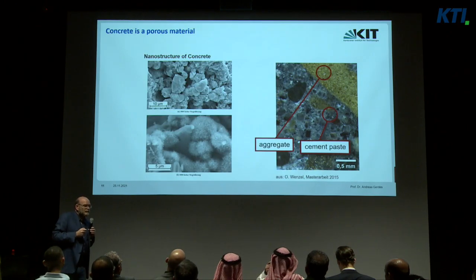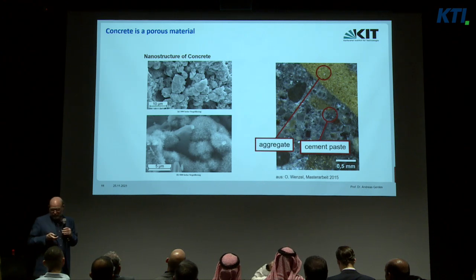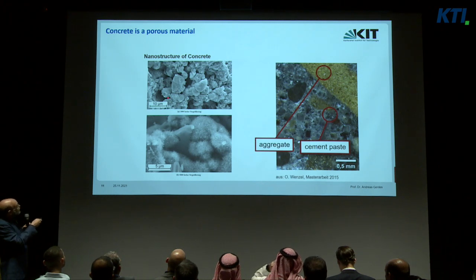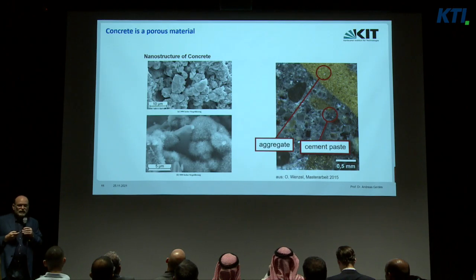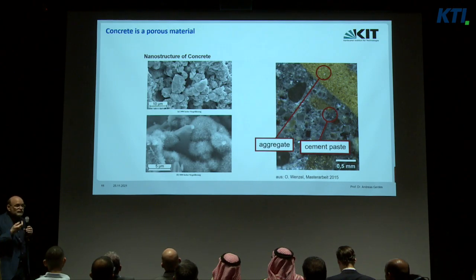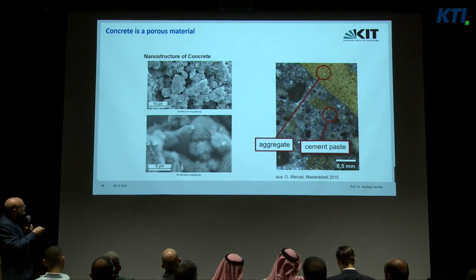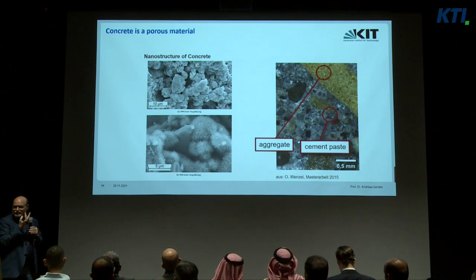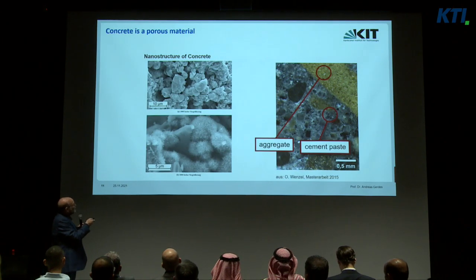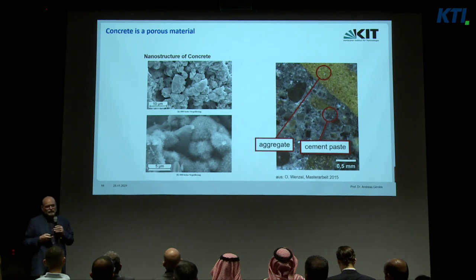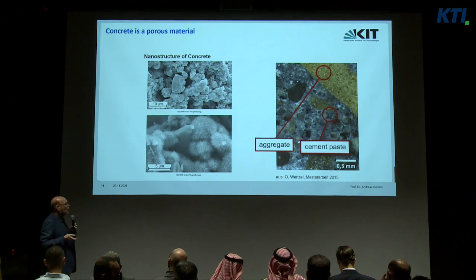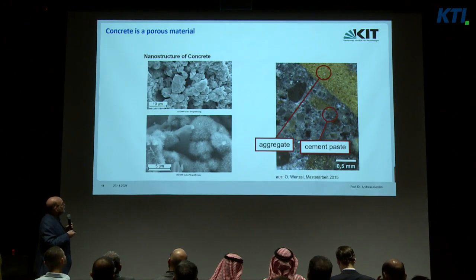Here are some figures about the structure of the cement. If we have a look at the pore structure, we can see there are a lot of pores with different diameters. So we have not one pore with one diameter, we have a pore size distribution. And here you can see the hydration products. It's like art. It's a really nice result of nature to show us these fine needles which form the CSH gel, which is a binding component in the concrete.